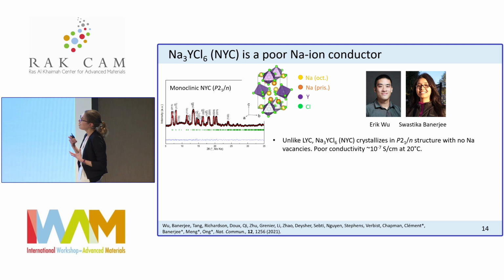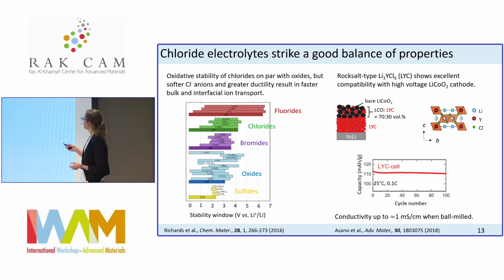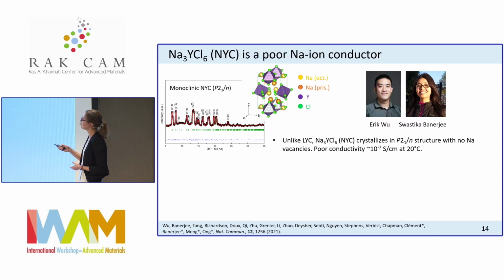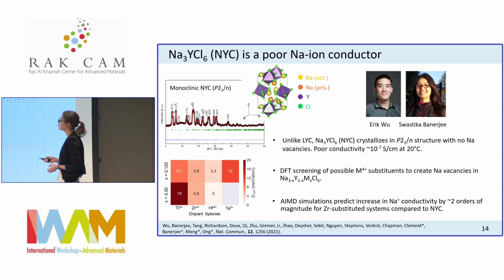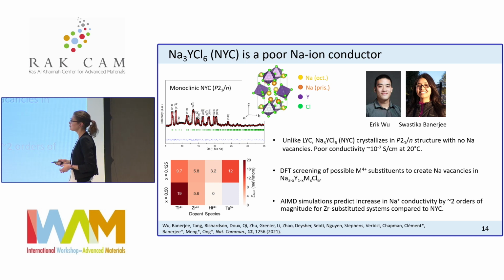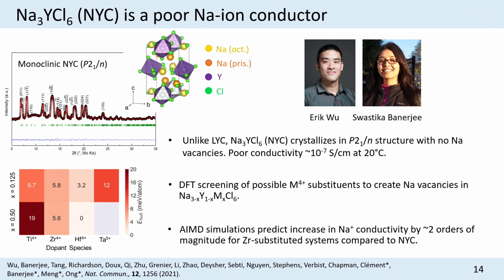material. And the problem with this is that now we have no sodium vacancies. In the lithium system, we had 2/3 of the lithium sites that were vacant, and that helps ion transport. In our case, we no longer have these vacancies, and this material is a very poor conductor for that reason. And so we decided to look at possible substituents for yttrium 3+. If you substitute yttrium 3+ by a higher valence ion, then you can induce vacancies in your material. You can create those vacancies.